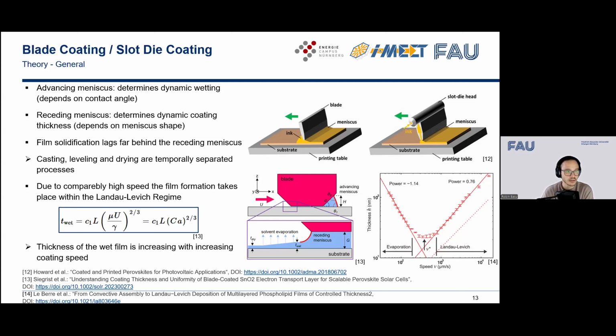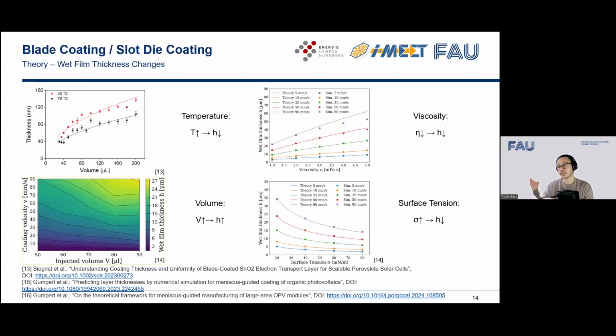So what else can we modify when we're talking about slot die coating and blade coating? We can modify the thickness by adjusting the temperature. As you can see on the graph on the top left, if we use 40 degrees for the same volume and the same speed, we end up with thicker layers compared to 70 degrees Celsius. So we can use the temperature to modify our thickness, but also to accelerate our evaporation. So we can use it in two ways.